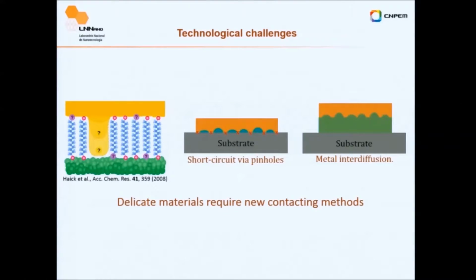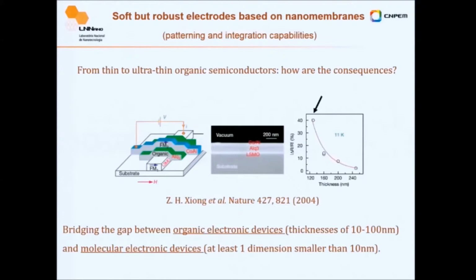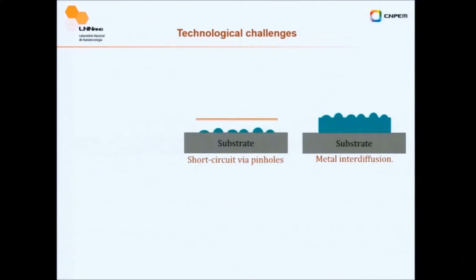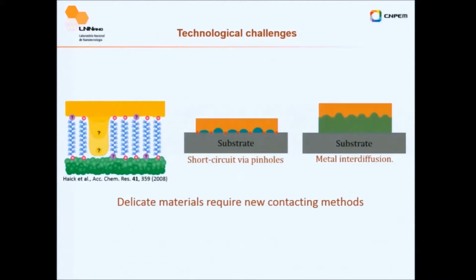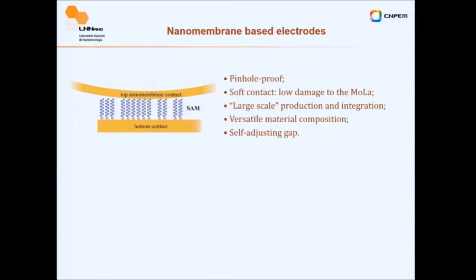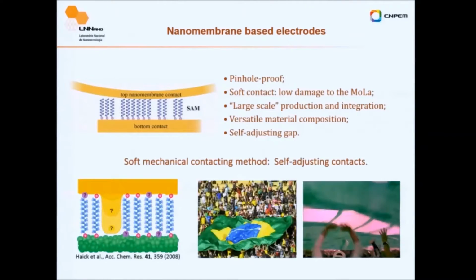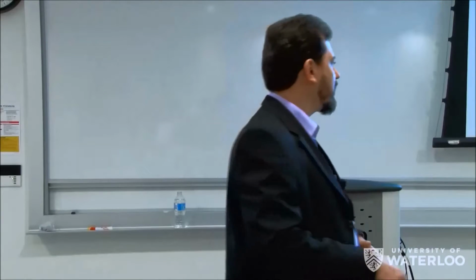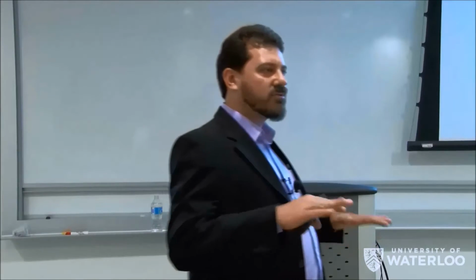Especially if you go to thin devices, if you think about a very thin layer, smaller than 40 nanometers, how can you be sure that your contact is across the organic layer? So then you came up with this idea of using a membrane to do this. The concept was simple. The bottom electrode is exactly what everybody else does. But the top one, you use a membrane for that. The advantage is that it is pinhole proof. Why is it pinhole proof? Because it's like a flag on a crowd. You lie on top of your molecules and you never touch the bottom. So even if we had some guys that are really not supporting Brazil and want to be sitting and don't want to hold the flag, doesn't matter, the flag will be there lying on top of the molecules.